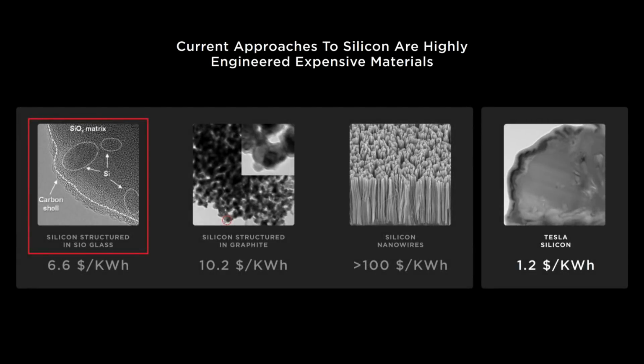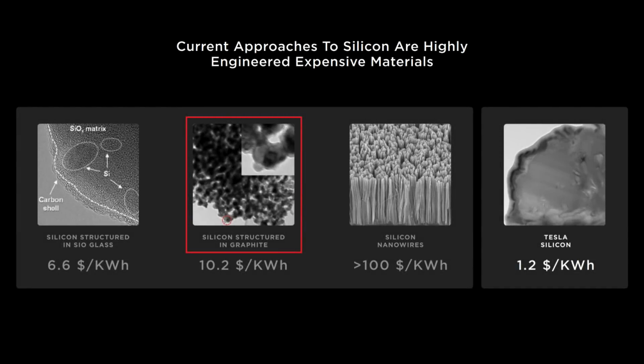So one is to keep the silicon in micron-sized particles, and then use, for example, carbon coating together with oxygen to try to hold together the silicon, and that has a lot of its own drawbacks. The other way people have been trying to do this is to make nano-sized silicon hidden, for example, encapsulated into an amorphous carbon matrix. And by that, you hide the silicon inside so it doesn't get into contact with the electrolyte, but you have to leave enough room for the silicon to expand and contract.